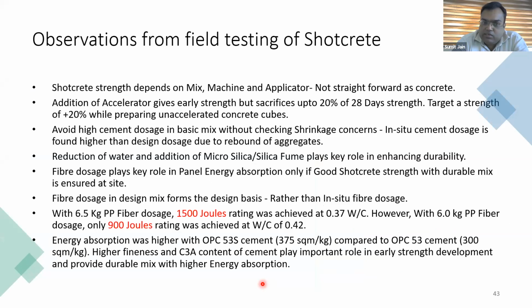Addition of accelerator gives early strength. Yes, it gives you early strength, but it sacrifices the 28-day strength by almost 20%. So whenever you are going in the field trying to establish a design mix, always target a strength 20% more when you are doing the unaccelerated concrete cubes. Say you want to do an M30 Shotcrete, you want to prepare a design mix for M30, you target M40 without any accelerator. The moment you add accelerator, it will go down automatically to M30. So this is a very important aspect which has to be kept in mind.